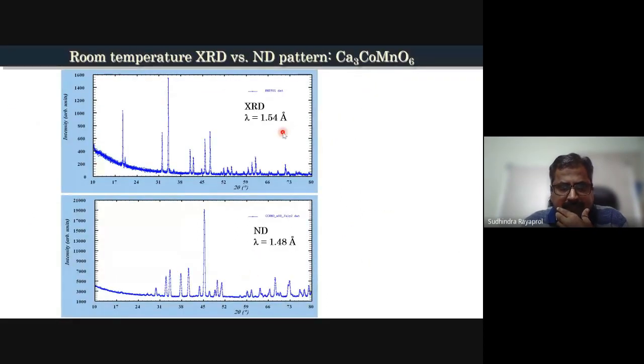So if we look at this XRD pattern, okay, this is for the same composition, calcium 3 cobalt manganese oxide, and we have measured at room temperature using X-rays at 1.54 angstroms, which is the copper K alpha wavelength, and we have done it on our diffractometer at Dhruva using 1.48 angstrom neutrons. If you see the difference in these patterns, they are for the same angular range, but you can see that for certain peaks, the intensity is very high in case of X-rays and very small in case of neutrons, and for others, in case of X-rays the intensity is very small and in case of neutrons it is very high.